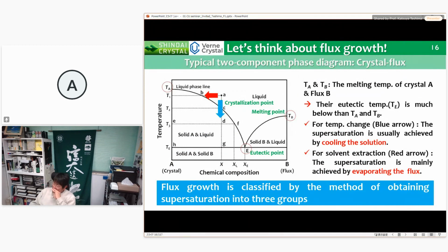Flux growth is classified by the method of obtaining supersaturation into three groups: slow cooling method, evaporation method, and temperature gradient method. For temperature change, shown by blue arrows, supersaturation is usually achieved by cooling the solution. In the case of solvent extraction, shown by the red arrow, supersaturation is mainly achieved by evaporating the flux.